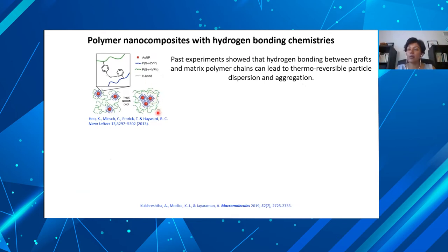So the green here would be the free or the matrix polymer, and the blue would be the graft polymer, right? So this is work from one of my collaborators' lab, Ryan Hayward. He used to be at UMass Amherst, now at Colorado Boulder. They had shown that hydrogen bonding chemistry between the matrix polymer and the graft polymer allowed them to create a thermoreversible polymer composite. So this is something we'd like to study and come up with cool designs and how we can make it so we can tune the thermoreversibility, tune the phase behavior.